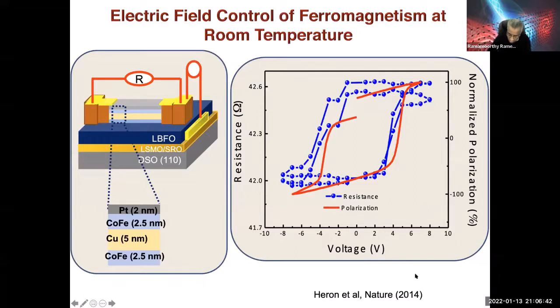Now, fast forwarding to 2014, this paper is the one that got Intel's attention. Basically what we showed in this paper was that you take a lanthanum-doped bismuth ferrite and put a spin valve on top of it, a very simple cobalt-iron-copper-cobalt-iron structure. And what we showed was when you switch the ferroelectric, shown in red, with an electric field, the spin valve resistance also changes. And using Jorge's theory, we said, look, the canted moment in the BFO is switching back and forth, and we're manipulating that. And this is what got the Intel folks' interest.